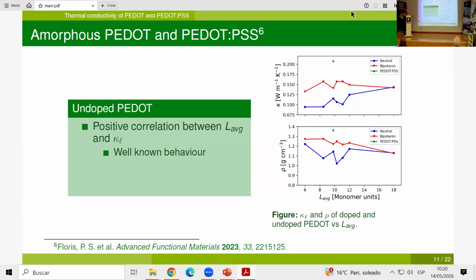And so what we found: we studied PEDOT in its undoped and doped forms. The undoped is here in these graphs with the blue line. We found some very well-known results for undoped PEDOT, which is that the lattice thermal conductivity increases when we increase the average molecular weight, or length, of the PEDOT chains. We also found a weak negative correlation between the density and the average molecular weight: as we consider longer and longer PEDOT chains, the density starts to decrease, even though the correlation is weak.